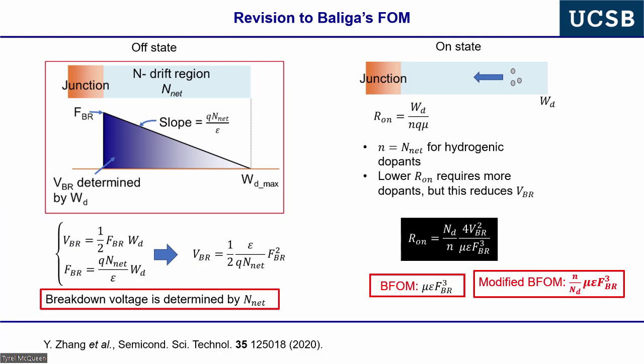The problem with this analysis originally, when Jay Baliga did it over 40 years ago, is that he assumed that all the dopants were shallow. And at the time he was developing his figure of merit, which is a remarkable figure of merit, he was working on semiconductors where all the dopants were shallow, okay? And so this is really what he did. But if you look at new wide and ultra wide bandgap semiconductors, we may not have shallow dopants. And the mistake that many folks have made, including the plots in the previous slide, is they don't account for the dopant ionization.